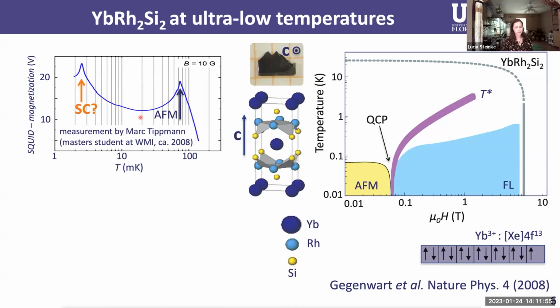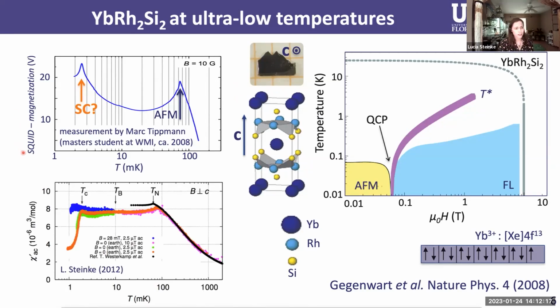So when I joined Frank Steglich's group as a postdoc, my first job was to try to find out if it was a superconductor. Now, one of the obvious things you think one might do is measure resistivity, but we decided to not do that as the first step because that's actually extremely hard at these temperatures and when the sample is a good metal. So instead, we decided to do another magnetic measurement. So instead of magnetization in a static magnetic field, we measured AC susceptibility in an alternating magnetic field.